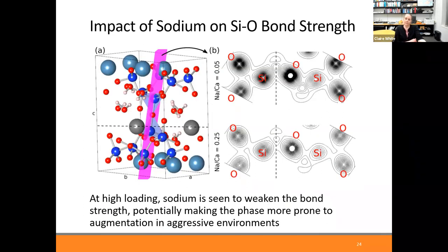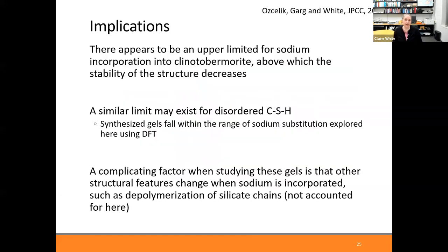We also looked at some other properties of the structure, such as the bonding strength. And so what we found was that with low sodium contents, you have stronger bonding between the silicon and oxygen. As you go up to really high sodium contents, then you're ending up with a lot weaker bonding between the silicon and oxygen atoms. So this would make it easier for these bonds to break because they're not as strong. So the implications from these calculations is there appears to be an upper limit of sodium incorporation into this structure, above which the stability of the structure decreases. And so a similar limit to the amount of sodium may exist in the disordered CSH gel structure.